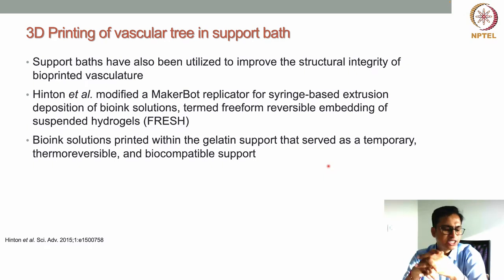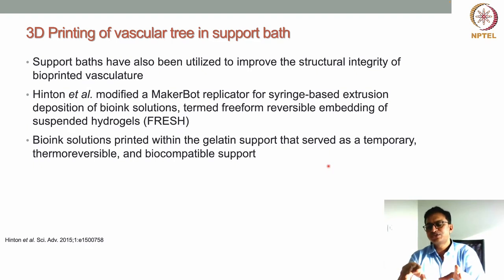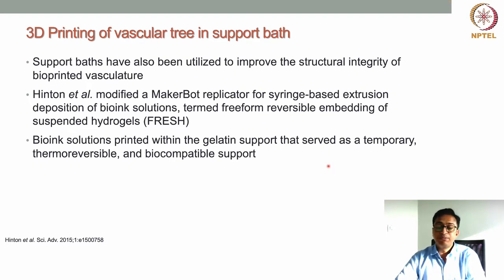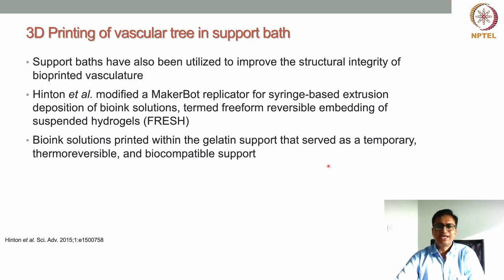They used a syringe-based extrusion system where hydrogels are loaded and pneumatic or mechanical pressure is applied to extrude the bioink. They modified a MakerBot FDM printer to house a syringe, loaded alginate material as a bioink encapsulating cells, and printed within a gelatin microgel support bath.